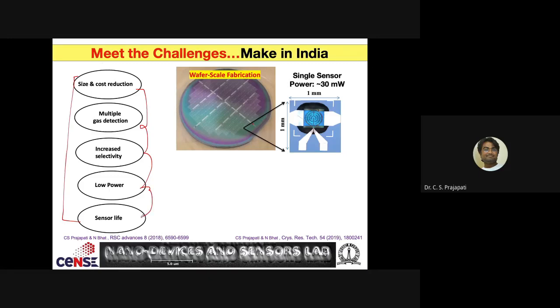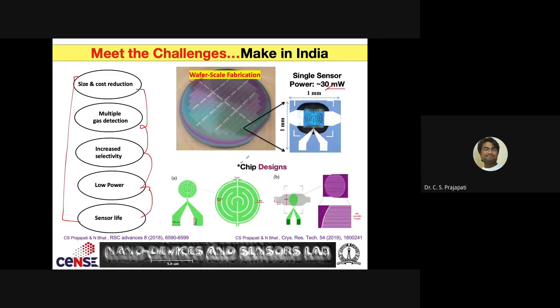Okay, so we made a wafer scale process. This is a 4-inch silicon wafer where you can see these small tiny devices, the size of 1 mm by 1 mm, 1000 micron by 1000 micron. This is one gas sensor chip, which uses around 30 milliwatt of power. We could reach 30 milliwatt because of the rigorous chip design we have done. Thanks to Rohit Soman, who was working when I joined this group, and he came up with a very nice idea here.